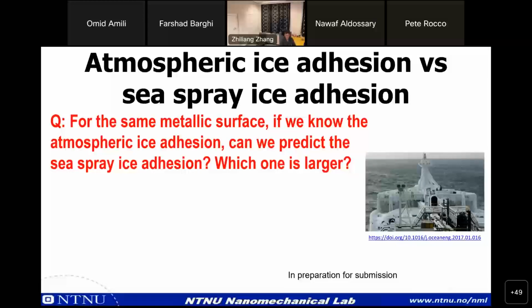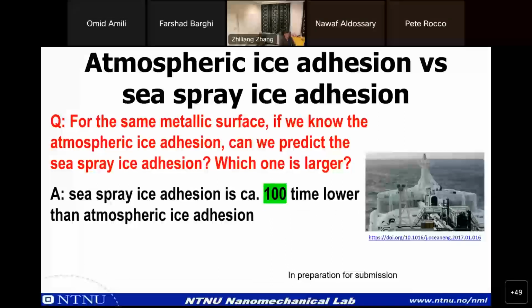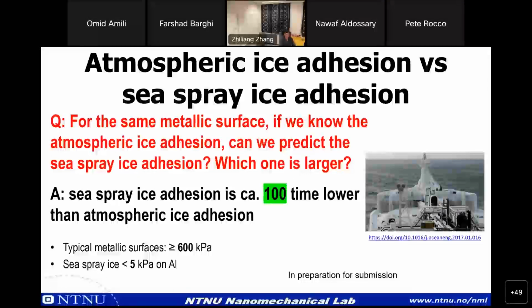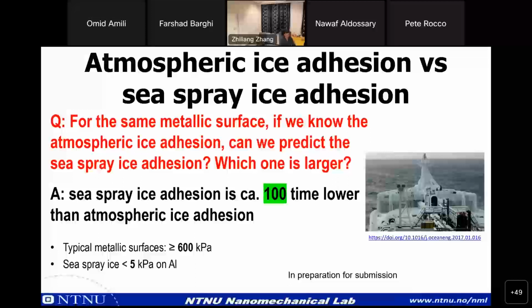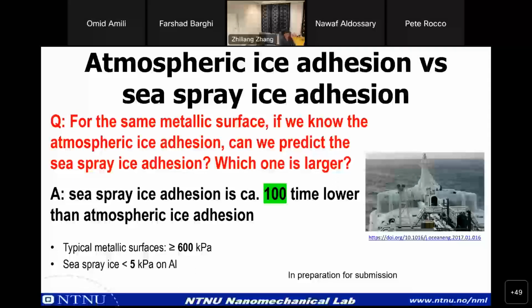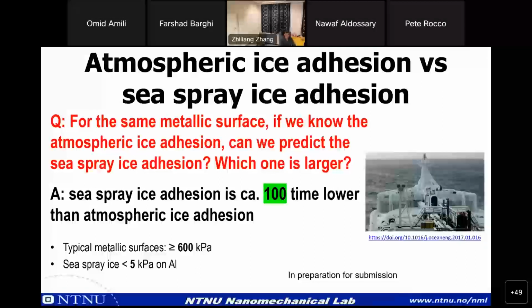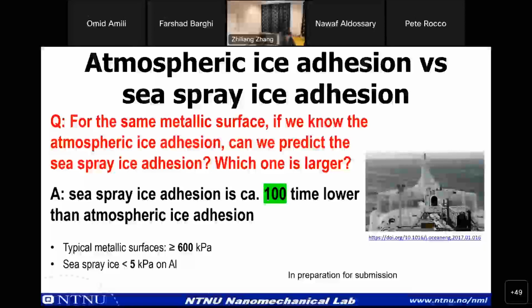I don't know if any of you have any answers to this question. Let me give you the answer. Sea spray ice adhesion is about 100 times lower than atmospheric ice adhesion. For example, for a typical metallic surface, for example aluminum, the ice adhesion would be 600 kilopascal. If we talk about sea spray ice, the ice adhesion will be less than 5 kilopascal. So this is a big contrast. For the same surface, we have 2 orders of magnitude difference.